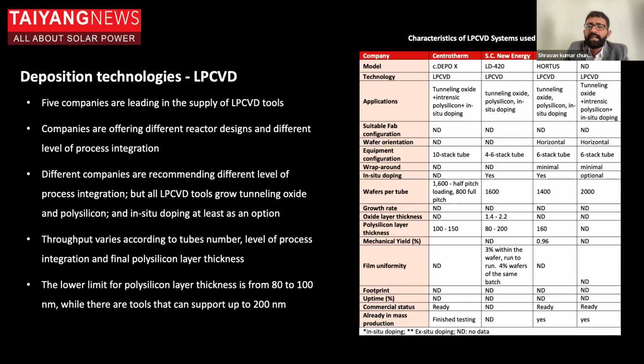So another important aspect of LPCVD is their ability to deposit thinner layers of polysilicon without losing uniformity. So layer thickness also influences this throughput. That's very important here. So now the current systems can deposit down to 80 to 100 nanometers, as you can see here.